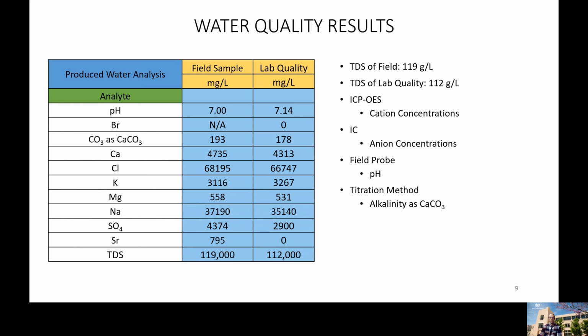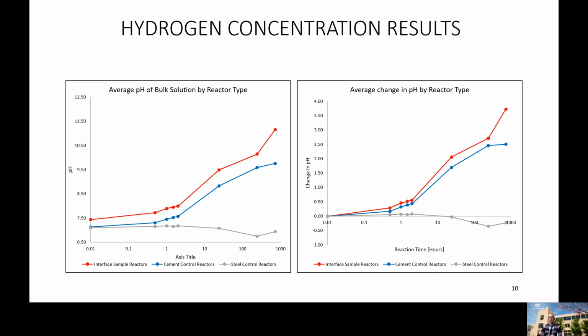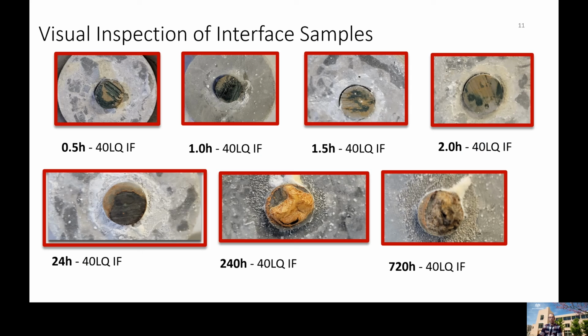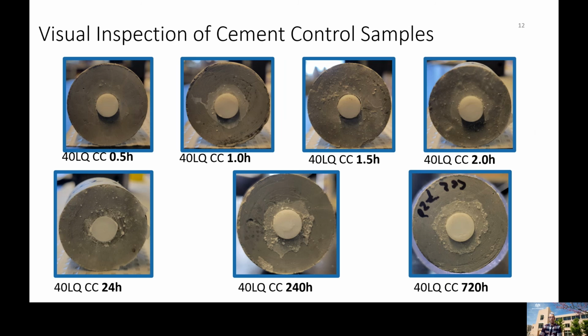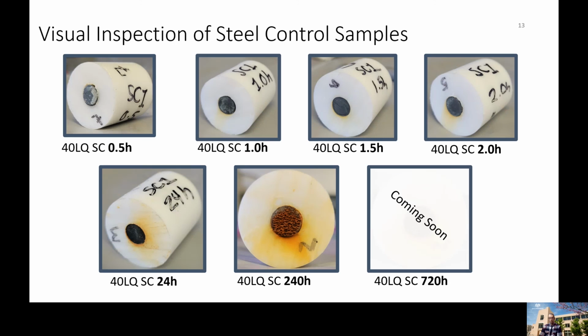So initial look at the water quality results. We've created a lab quality brine that closely matches our field sample. We are tracking the pH over the reaction times, and we are seeing that cement causes the pH to go up, while steel-only reactions cause the pH to decrease slightly. So just a quick visual inspection of some of these samples that we've created. We can see that there is an increase in visible precipitate over the time of reaction, and this was also seen in the control samples of cement and steel.